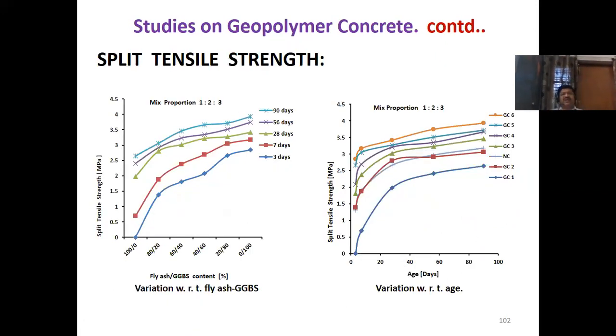And of course, normally we will not stop at finding only compressive strength. We find the other mechanical properties like split tensile strength, etc. So we conducted split tensile strength tests using cylinders. The relation between the split tensile and compressive strength was almost the same, right? So it's around 4 MPa. Here also it is around 4 MPa. This is the increase in GGBS content. This is with the age, right? This is split tensile strength.